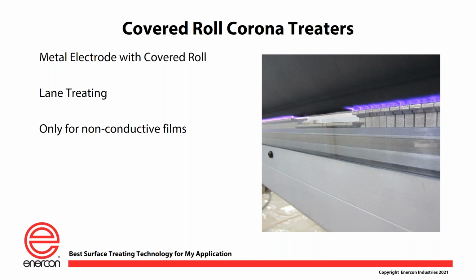The one downside to this, if you want to call it that, is it really doesn't work for conductive films. You can only use it for non-conductive. If you had a metal substrate that you tried to put through here, you would have a problem. The corona would just arc. The electrode would just arc to the metal and shut the treater off, and you wouldn't be successful. So if you have a standard non-conductive film, these metal electrode systems work great for that.